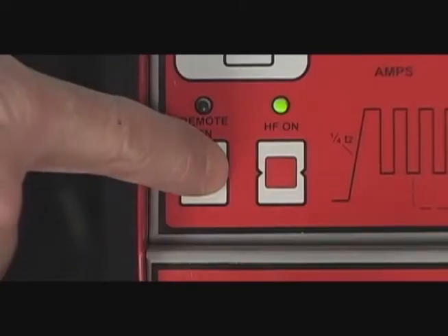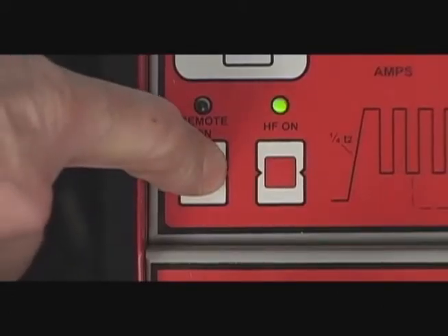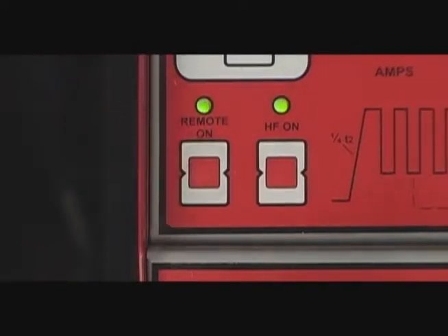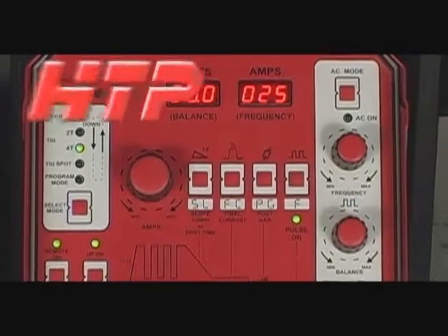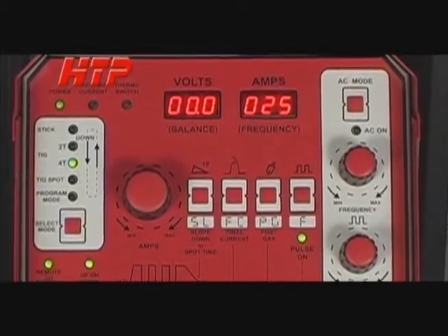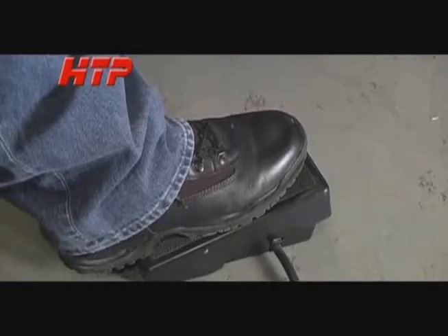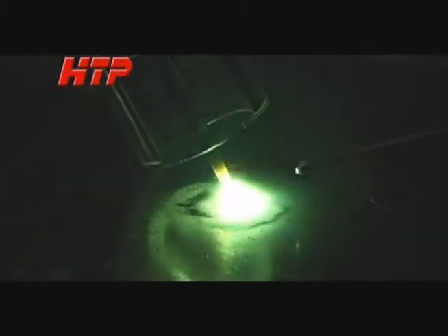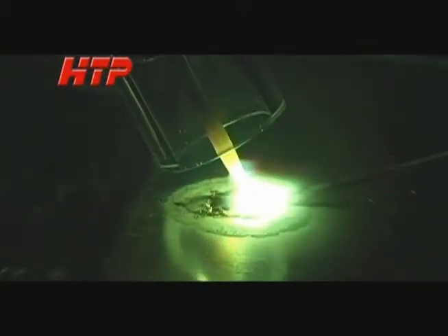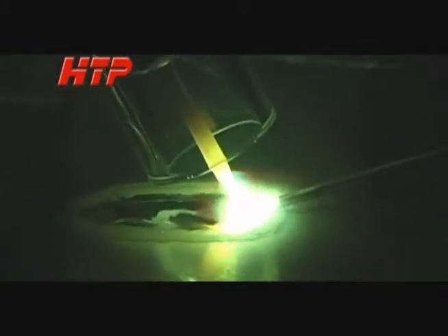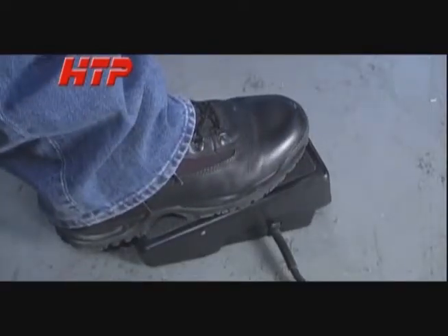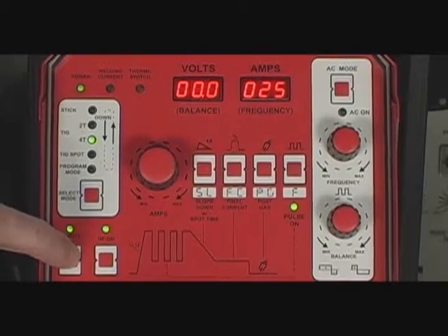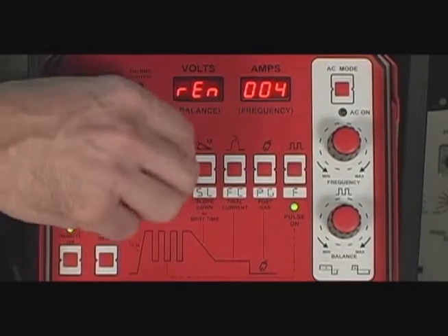Depress the remote on button for 5 seconds until the green indicator lamp turns on. The display now reads the starting amperage, which we just set to 25 amps. Now, when you fully depress the foot pedal, the maximum amperage will be 100 amps. This makes the foot pedal less sensitive and makes it easier to control your pedal. Now I am going to set the starting amperage back to 4 amps.